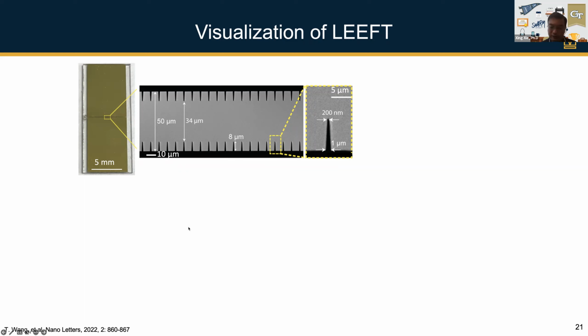So what we have done here is that we moved the system onto microfluidic chips. What you are seeing here is basically a glass slide, a piece of glass, and then you coat the surface with a very thin layer of gold. It's a standard manufacturing procedure that we need to do in the clean room. We can see here you have two bulk coatings of gold that function as contacting pads. This is just 5 millimeters, a very small piece of glass, right? These two pads are used for the connection.